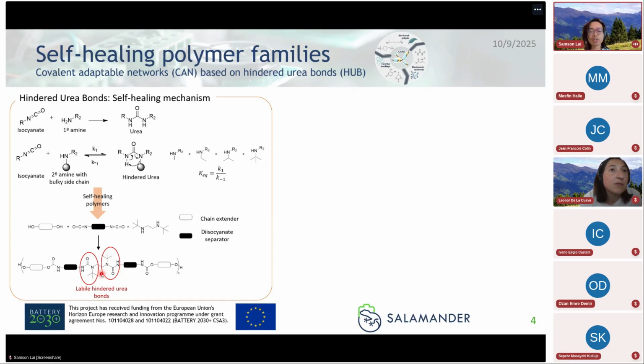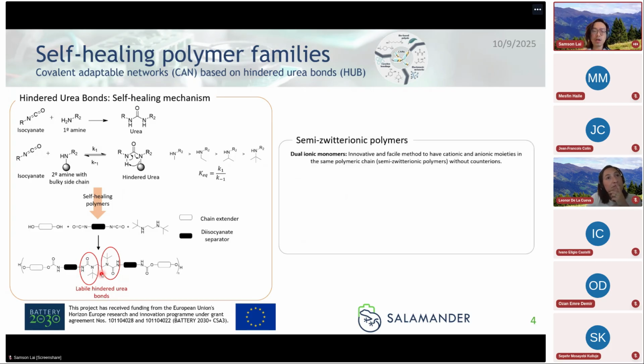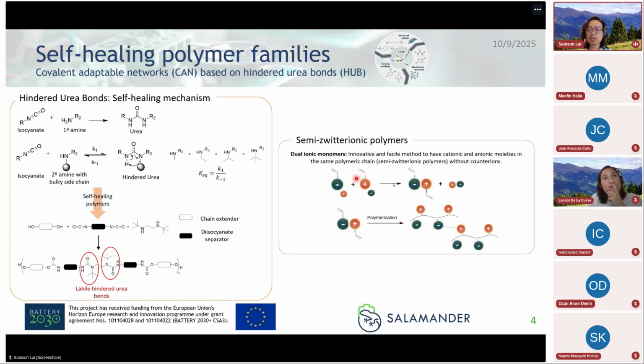The other type of polymer that I was talking about, semi-zwitterionic, is basically made of dual ionic monomers. So it's a single polymer chain, but on that single chain, you have both cationic and anionic moieties. And that's what creates these semi-zwitterionic properties. You can have ionic interactions between polymer chains, and these polymers can come apart because they're using ionic interactions, but then they can come back together, and that's how you get the self-healing properties. And again, you can tune these polymers based on chain length and these kinds of things to adjust those self-healing properties.